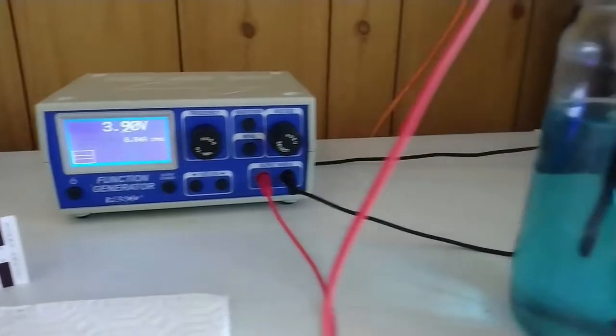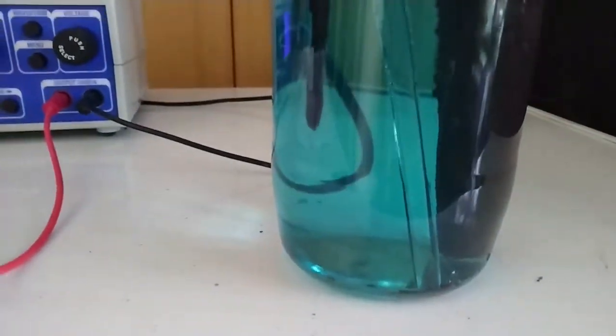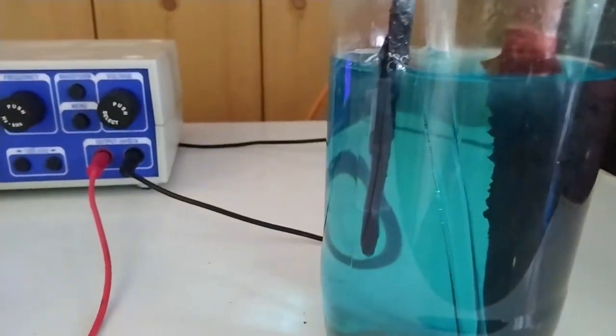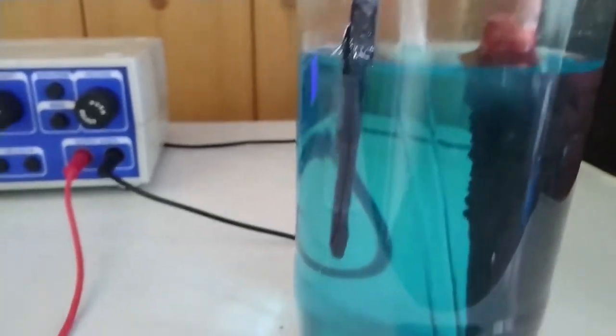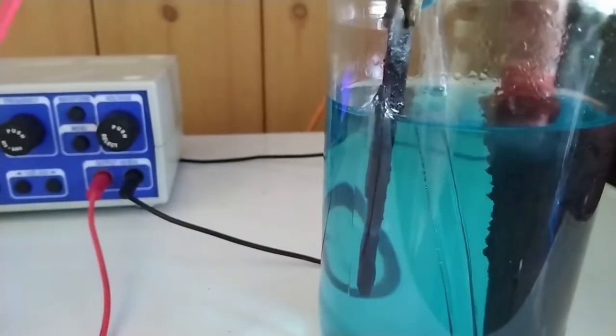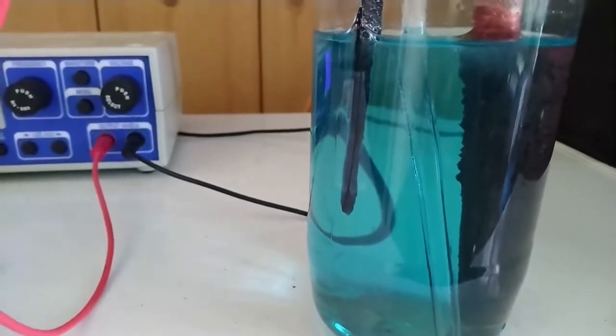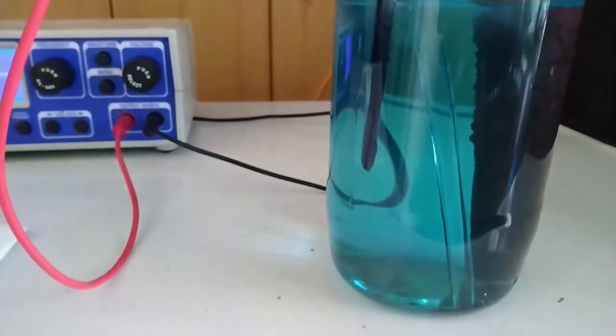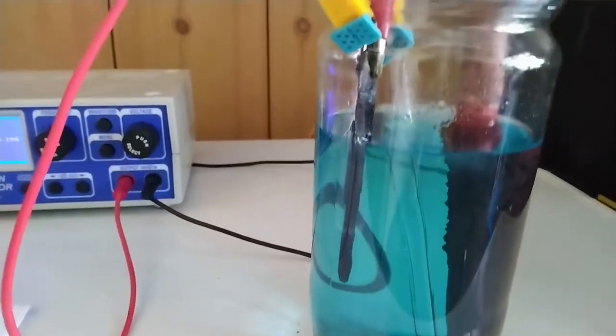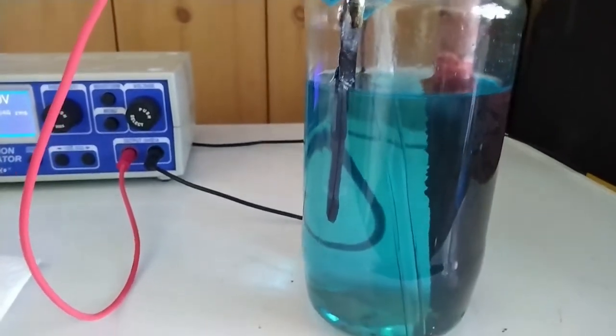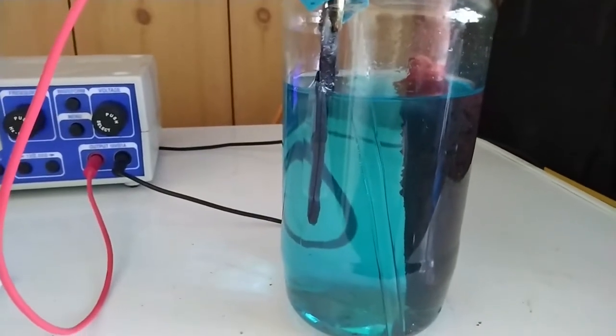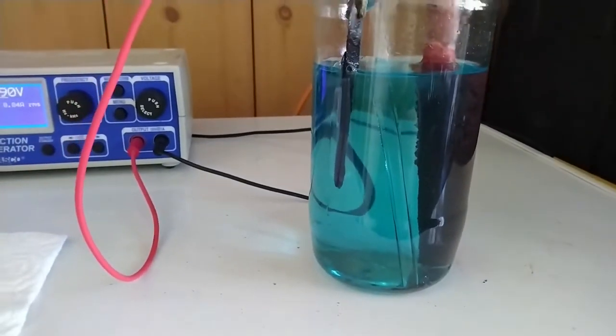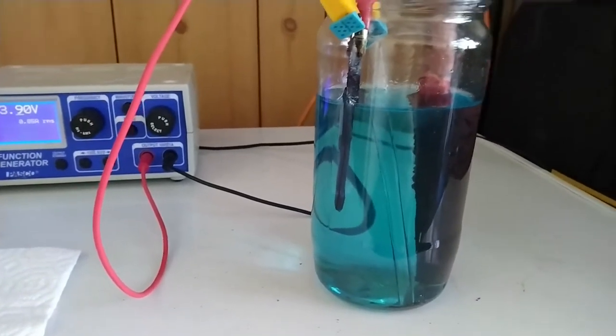So the conductivity increased, and now all the remaining copper sulfate has been dissolved. Now you can see that there is some residue that comes from the cathode, the copper that is not sticking to it, so it falls in the jar. And also there's a little bit of the coating on my lead electrode that fell, but it's perfectly fine. Once again, this doesn't dissolve at all in the solution, so we will be able to filter this out and obtain a perfectly clear solution. Also, the solution now is being depleted, so it started to clear out, and we have to wait a few more hours for the electrolysis to be complete.